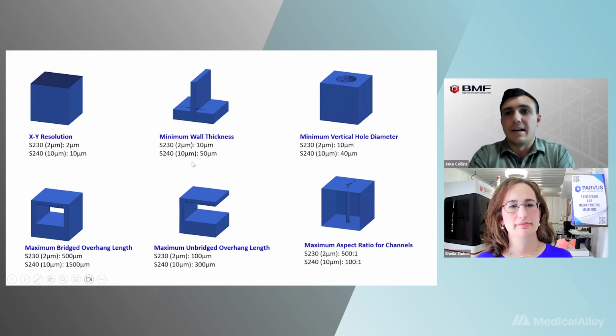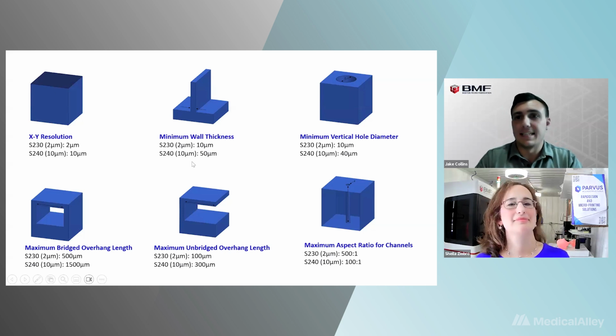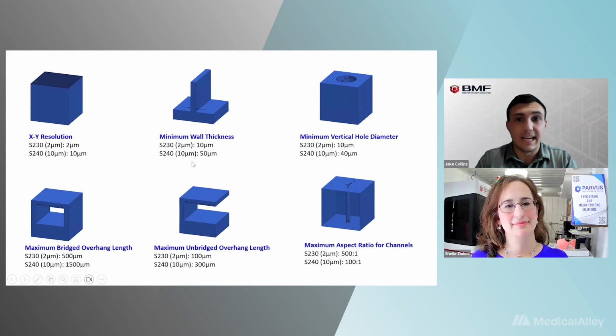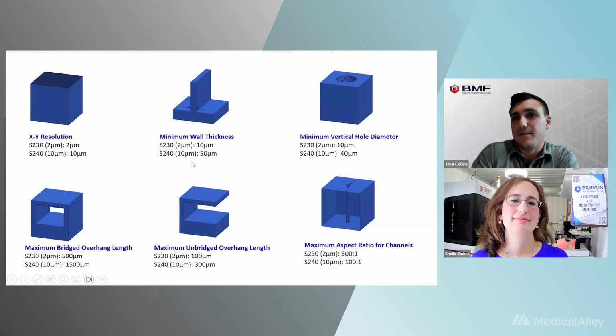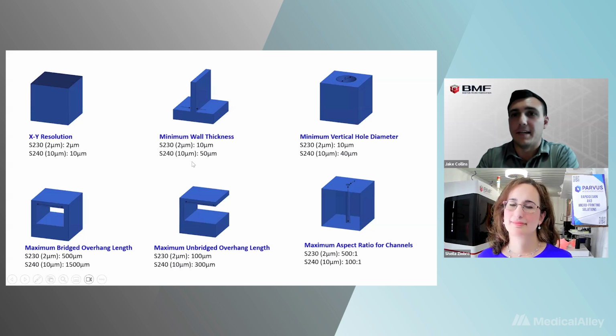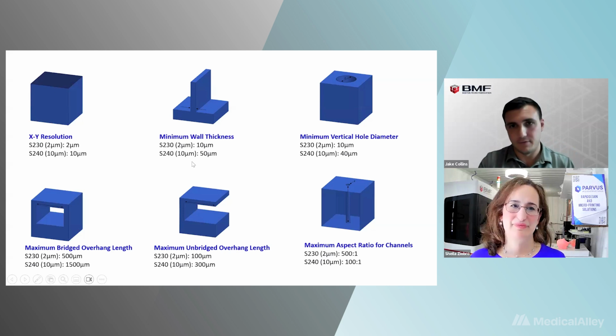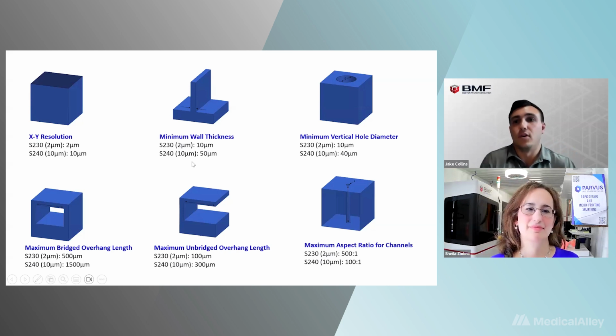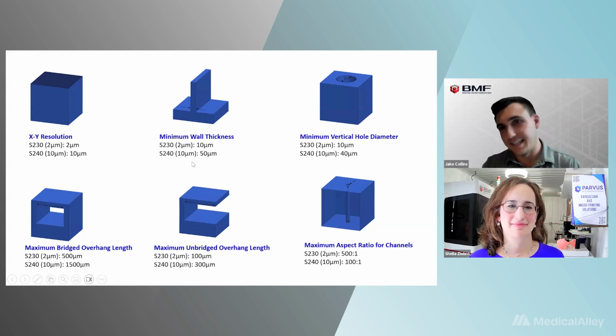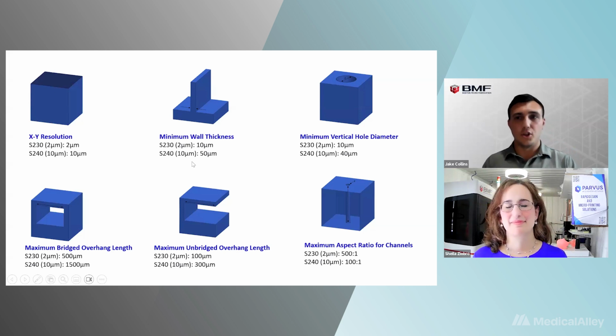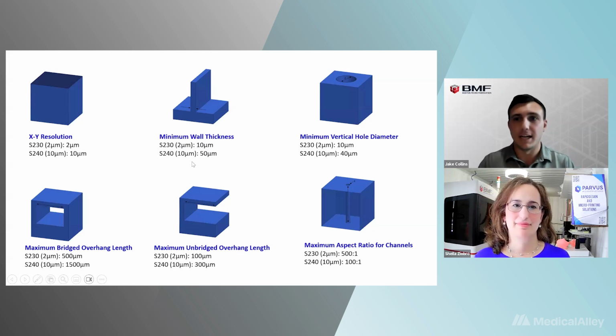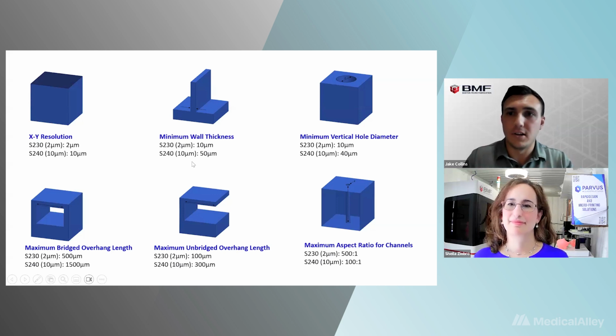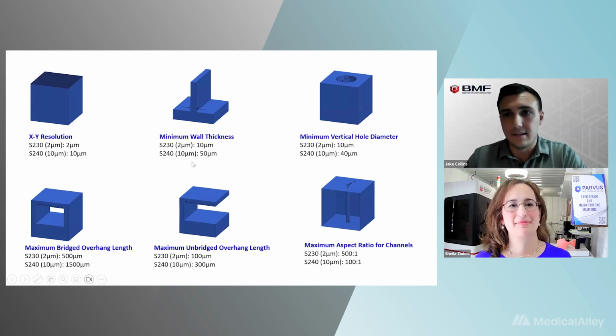And typically where a lot of these design guidelines come from is that you want about 5 pixels to make a feature. That's more just to create good structures with vertical holes. If you have 2 pixels across, you're going to get a little bit of a pixelated design, purely because of the limitations of the projector. That's why we have different resolution systems that go even further down. So if you're looking for things that are hundreds of microns in feature size and keeping those high tolerances, you're looking at the 10 micron system. But if you need something with even finer resolution and even tighter tolerances, then you're looking at the 2 micron system. So there's a wide range of freedom you have on all of those sizes.